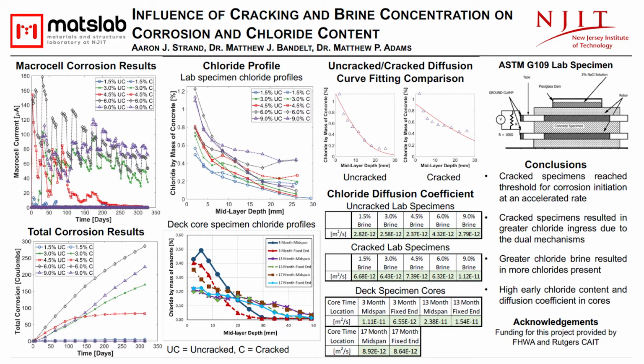This is compounded by cracking of the concrete deck due to conditions such as live loading, thermal loading, and concrete shrinkage. These cracks can develop at early ages of a bridge's lifespan, even soon after initial construction. The depth of the crack will provide an effective reduction in the cover depth above the reinforcement, and at worst may provide a direct path to the reinforcement for the chlorides.